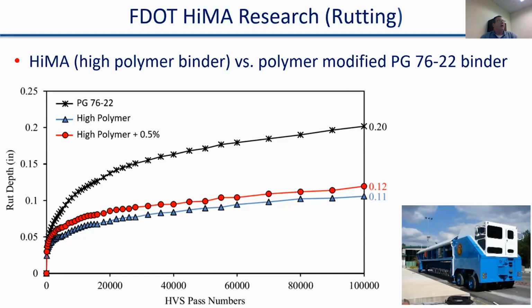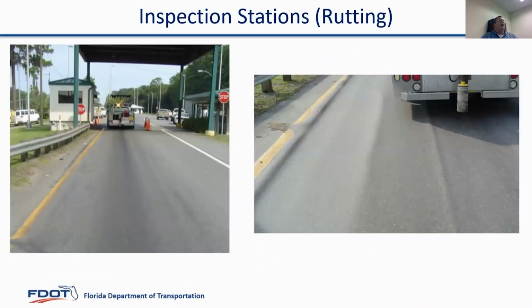What's also neat is we saw we can make a richer mix by increasing the asphalt content by 0.5%, which would normally kind of give you a little bit of pause with respect to rutting resistance. We really didn't see any increase in the rut depth there. We only saw 1/100 of an inch increase. So again, you get really good rutting resistance with the high polymer binder as we saw here in our research and also with some of the research Dr. Tim pointed out earlier. And again, where would we use it?